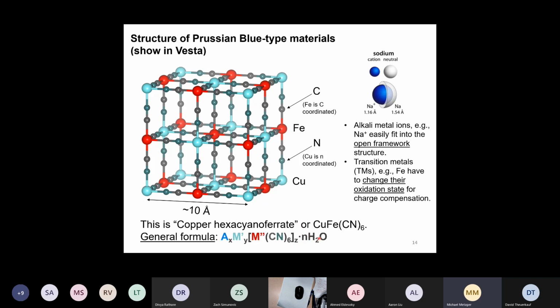And then we also have so-called interstitial water. These open sites in this framework are also called interstitial sites, and water can be present here from the synthesis. And the unit cell volume of this material would be 10 angstroms by 10 angstroms by 10 angstroms, so 1,000 cubic angstroms.